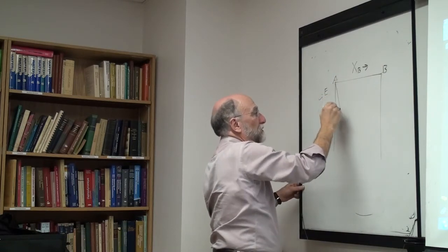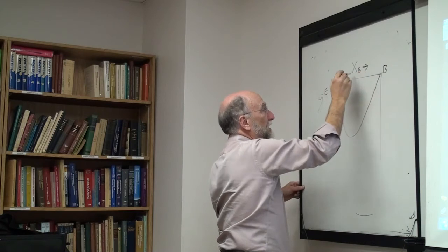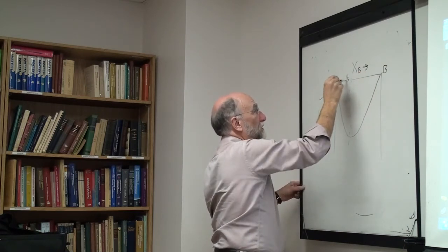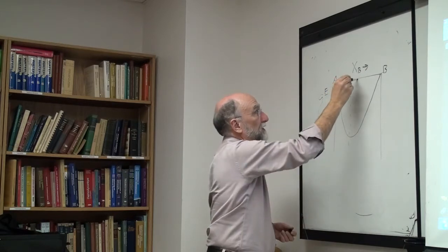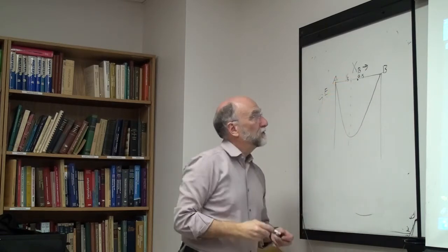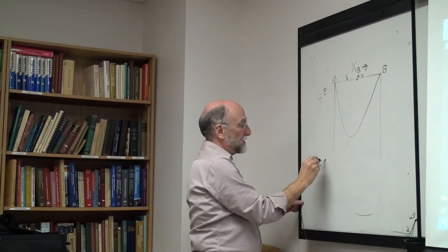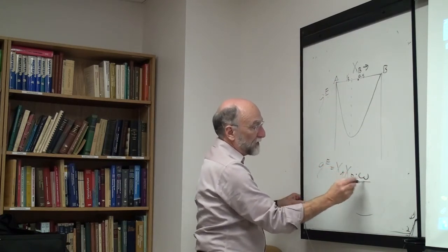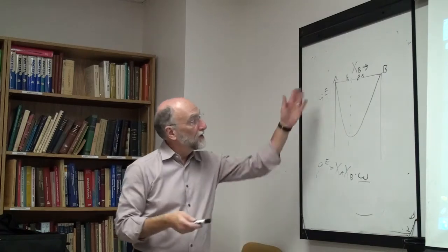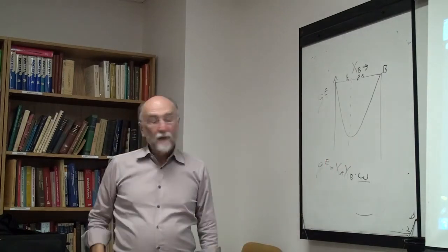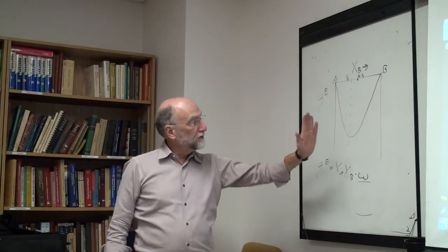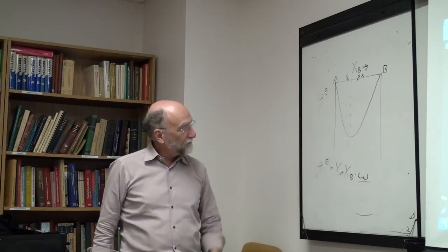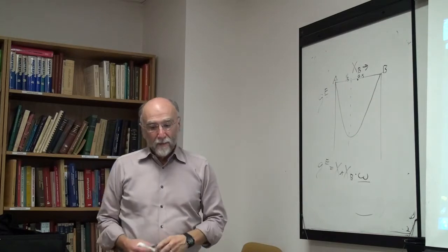Let's say you have a minimum in your GXS function. The minimum is coming somewhere around a third, or it's not at 50% anyway. If your minimum is at 50%, then you say GXS equals XA XB omega, where omega is constant. That will give you a minimum at 50%. Let us say that your minimum is not at 50%, when it's moving over towards 1/3.